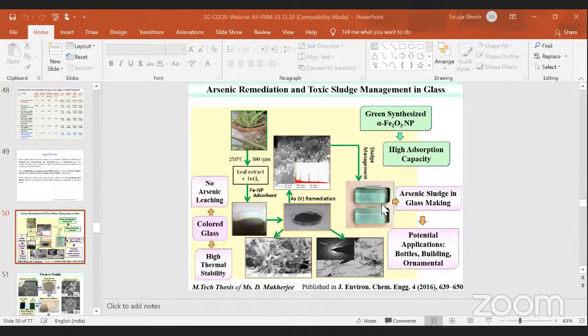And we found that up to a considerable percentage of the arsenic-loaded sludge can be immobilized in the glass matrix. The glass is a safe option for toxic material immobilization. That's why nuclear wastes are immobilized in glass. So this work is very interesting, as well as it carries strong potential for immobilization of the arsenic sludge, and this colored glass can be used for bottles or building applications as well as ornamental glass items preparation. The leaching study showed no arsenic leaching was observed in the glass, and these colored glasses show high thermal stability.